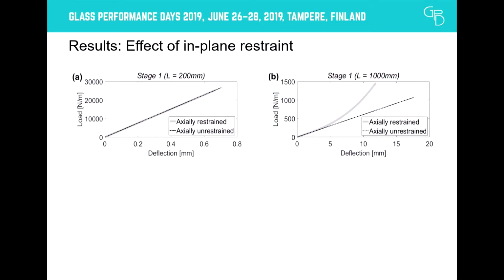Next, we assessed the influence of axial restraints for each stage independently. So in the first stage, which is the unfractured stage, we can see that it depends on the span length. So we consider two separate spans, a short one that is 200 millimeters long and a long one that is 1 meter long. So obviously, as expected in the short span, the membrane contribution is negligible, while for the long span, we can see that membrane action is participating in the response. I should mention that these deflections have been derived by solving the nonlinear differential equation using Galerkin method.